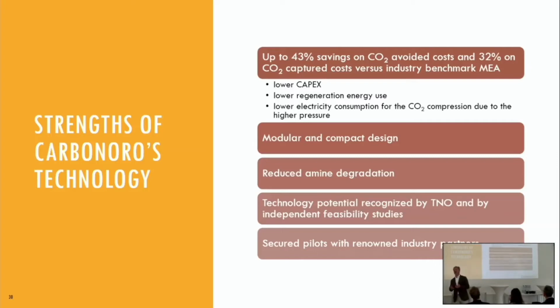What we have done with GCCA, and we worked with 6 different members of GCCA. First, we worked on defining 2 representative cases for GCCA, building on the CEMCAP specs, a 20% case and a 30% case. Looking at an 800 kiloton, more or less, CO2 flow in the flue gas and capturing more than 90% of it, so 730 kiloton per annum of CO2, with a CO2 purity above 99%.